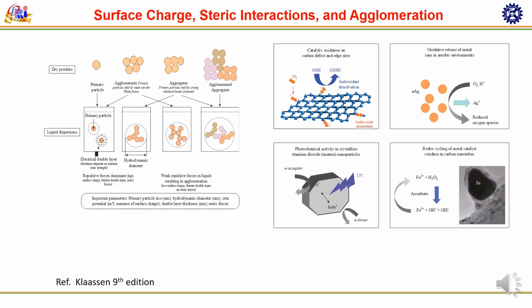Also, we can see the photochemical and redox activity. Titanium dioxide nanoparticles, when exposed to UV light, generate electron-hole pairs. This pair's redox activity produces reactive oxygen species. This explains why titanium oxide nanoparticles are photoactive and can damage cells under sunlight.